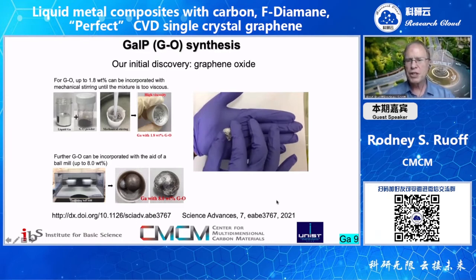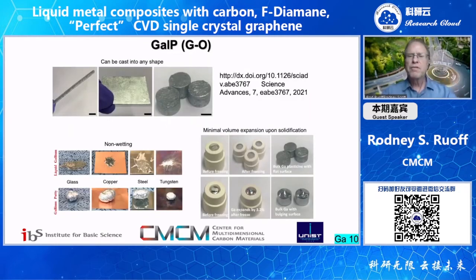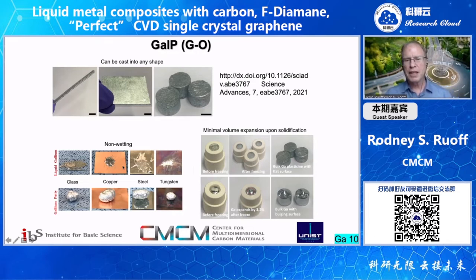In that movie, you're watching Chun Hui's hands as he manipulates the putty-like material he's made. Gallium and indium — and their eutectic with tin — are liquid metals with interesting challenges. Gallium will readily amalgamate with almost every other metal, which can be a good thing but can also be problematic. If you put gallium on copper, it's going to spread and leave a residue. In contrast, our putty-like material can contact the same substrates and not leave any residue and not really stick.